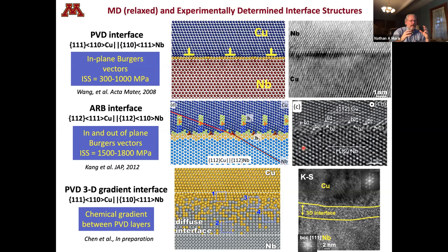And at the end of the day, you still have to relieve this certain amount of elastic stress between the copper and the niobium. So this configuration is one that relieves that mismatch for the crystallographic orientation that we have between copper and niobium in this ARB configuration.